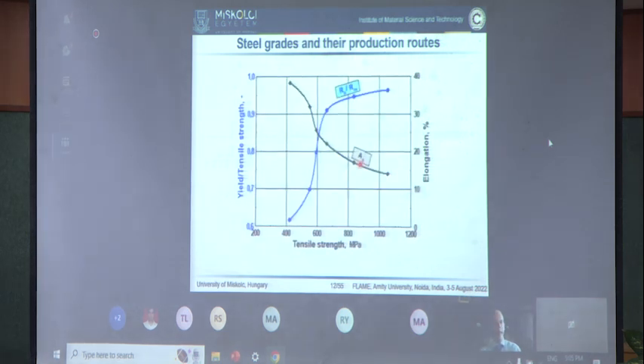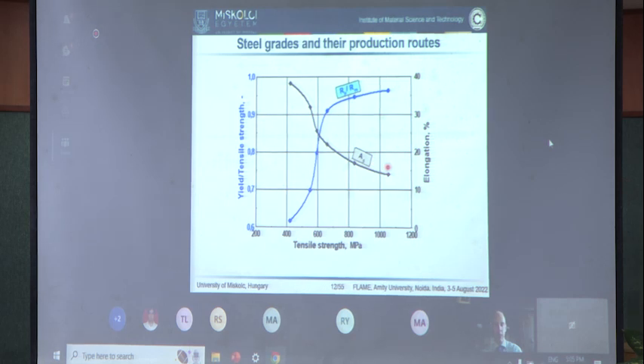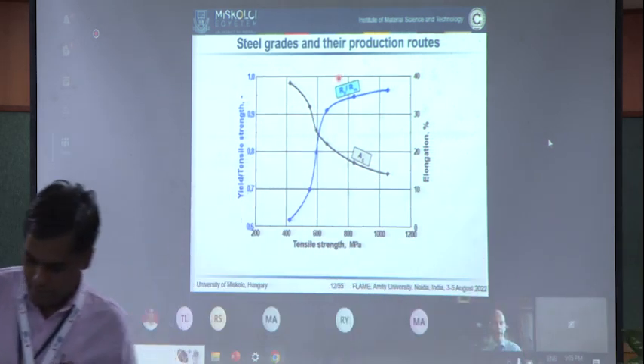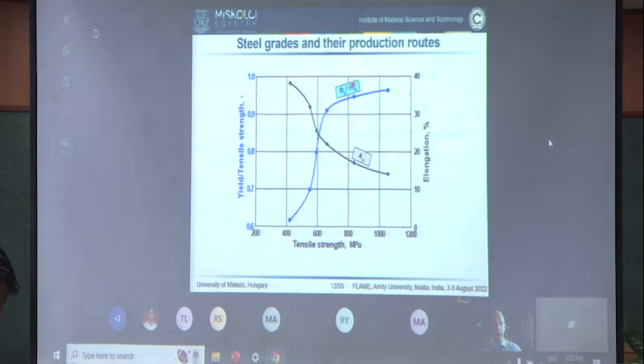When we would like to apply high-strength steels, we should consider that with increasing strength, generally the elongation, so the ductility, is reducing. And if we compare the ratio of yield strength and tensile strength, we can see that above 600 MPa, this ratio is quite close to 1, which means there is no plastic reserve in the material, so there is no difference between the yield strength and the tensile strength, and in parallel the ductility is reduced as well.